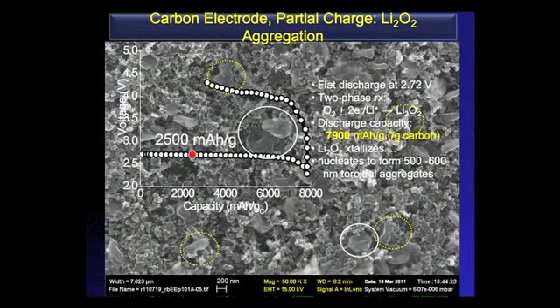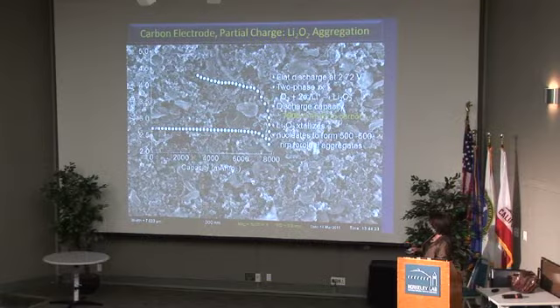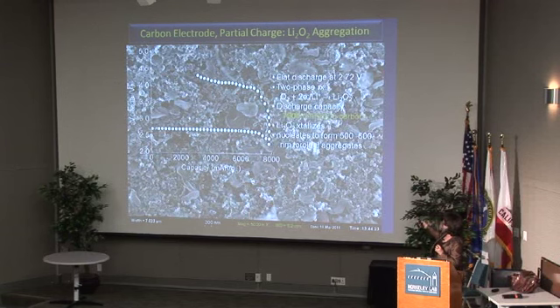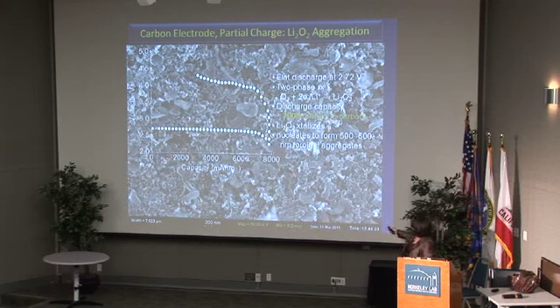I won't have a lot of time to tell you about this, but I'll just show you some nice pictures. So this is an uncatalyzed system, and this is just carefully designed carbon. That's all there is to it. So you see a nice flat discharge potential exactly where it's supposed to be, no slopes that indicate all kinds of electrolyte messes. This is characteristic of a two-phase reaction, as one would hope. And it is characteristic of peroxide formation, and we see this in the XRD. It's quite abundant. And this gets to about 7,900 milliamp hours per gram of carbon because it's a nicely defined carbon.